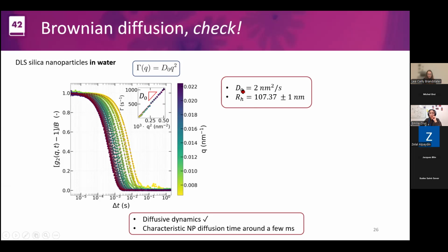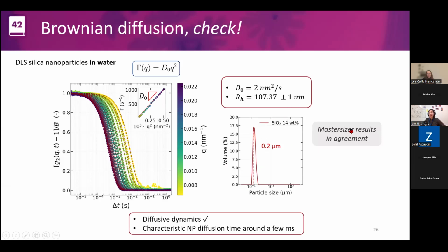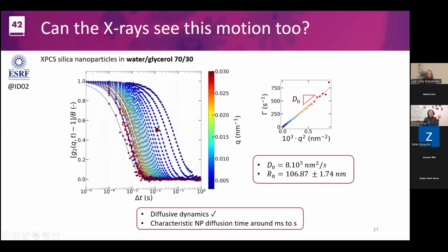The slope is the diffusion coefficient, like I showed in the equation. We get our diffusion coefficient, and thanks to that, the hydrodynamic radius of the particles. And we're very happy because it looks exactly like what we said in the very beginning. We said that our particles are around 200 nanometers, so it seems okay, they're around that size, and they have a slight polydispersity. I did a Mastersizer experiment, which is in agreement with that. So I'm pretty happy that the dispersion looks good. The particles are diffusive, and there's a characteristic nanoparticle diffusion time of a few milliseconds. Now we ask if the X-rays can see this motion too, because we have these nanoparticles in the soft glass, but it was white, so it would be difficult to perform the experiment with dynamic light scattering.